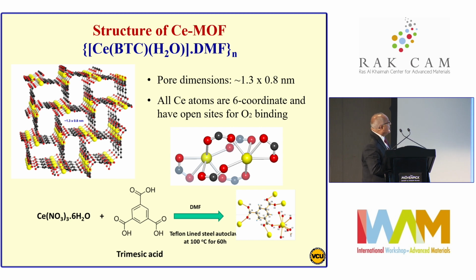So the first system we used to study this reaction as a support was a cerium-MOF. Cerium-MOF is developed where all the cerium atoms are coordinated with open sites for oxygen binding, and it can be made from a reaction of cerium nitrate and trimesic acid, as you can see here, in DMF. This MOF actually has a very low surface area, maybe 60 or 70 meters square per gram, so it's not that useful, but there is a way that we can increase the activity and the tuning of the properties of this MOF by incorporating it in a hybrid structure, as I will show you next slide.